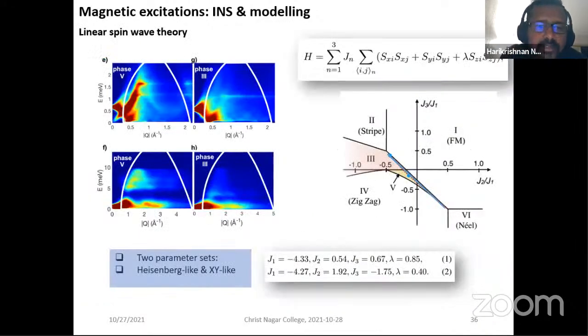Now there are ways of analyzing that by simulating what type of excitation can form if you assume certain energy-dependent Hamiltonian for this honeycomb. The result shown in this slide is after linear spin wave theory analysis. At the bottom, we have taken specific energy values for the exchanges J1, J2, J3. These are precisely the constraints that we were talking about in the first few slides. If we have these energies as the constraints for the spins arranged on a honeycomb, what type of ground state and excitation do we get?